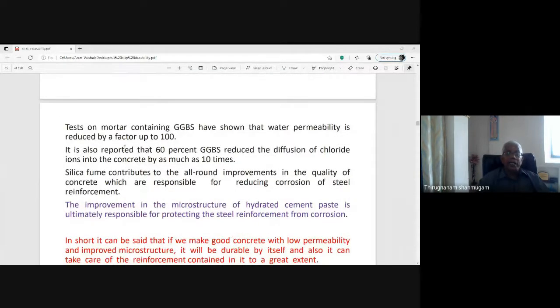Tests on concrete or mortar containing GGBS have shown that water permeability is reduced by a factor of 100. So permeability is 100 times lesser; the concrete is completely impervious. It is also reported that 60% GGBS reduces the diffusion of chloride ions into the concrete by as much as 10 times. Chloride ions are also reduced about 10 times.